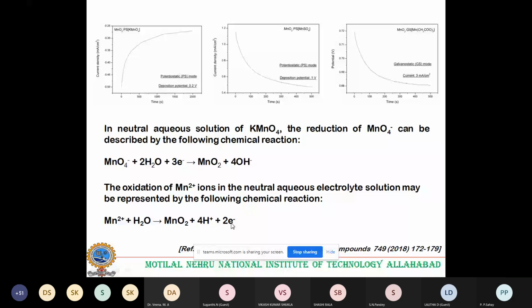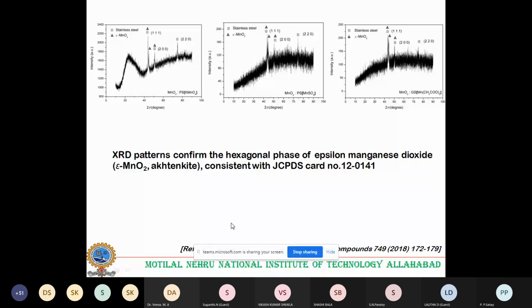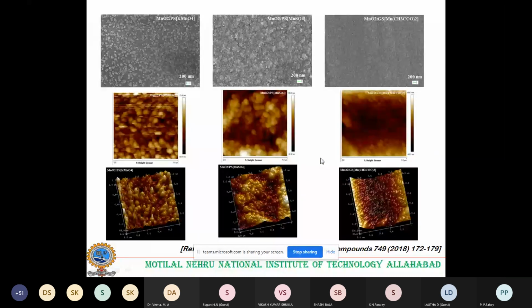Now, like the previous one, we go to the XRD. We carried out the XRD for all the three, and we found that in this case, hexagonal phases of epsilon MnO2 are present. Here again, we carried out the surface morphology of the film by both SEM and AFM. In the SEM, this is the same figure as in the KMnO4 case. These two are new ones. This is for manganese sulfate. This is for your manganese acetate. So the morphology is different here. Even in the three-dimensional figures, the morphology is different. So the topography pictures are different.